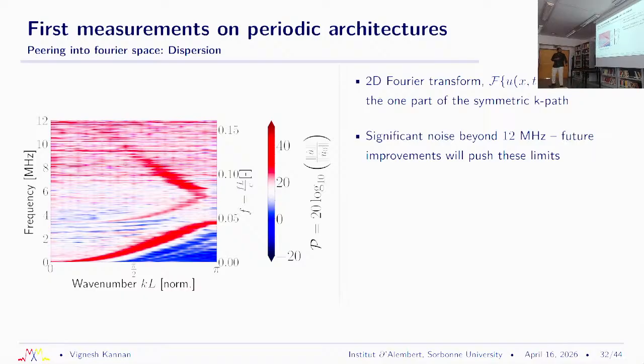This is from experimental data, and if I overlap this with the finite elements, which I'm not sure you can see very well, but you can see these blue lines, which is from finite element calculations, we see a near perfect match, with the exception that we're seeing this, the green lines are from out of plane modes, right? We shouldn't be seeing these intensities corresponding to these green lines in our experiment because we were making a measurement only along one line. So we should only be sensitive to one direction of the k vector. We were seeing some of these other modes which we believe is scattering from defects around our excitation point. Again, this is another detail that we can discuss further.